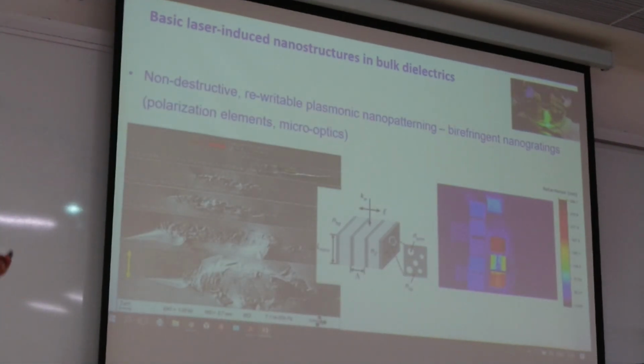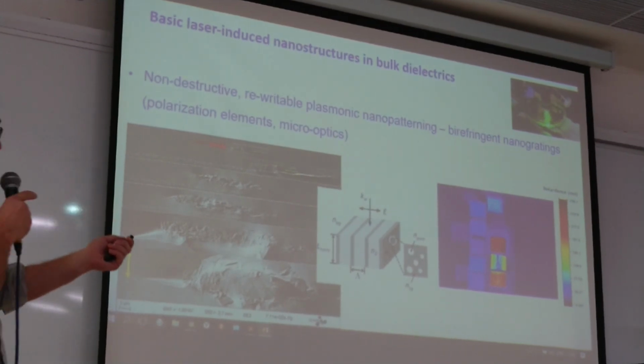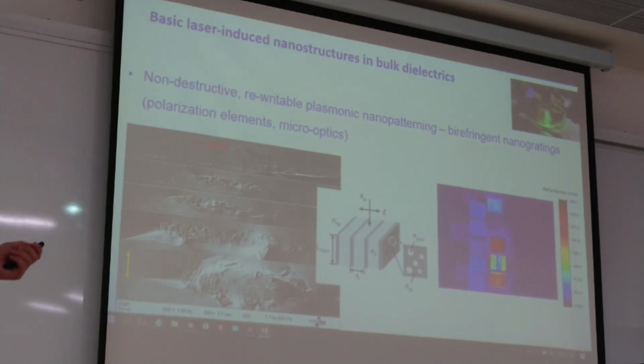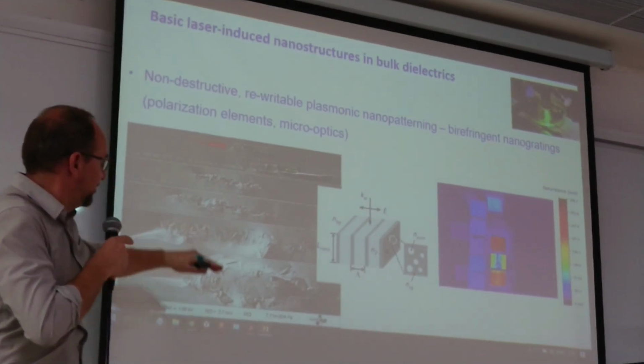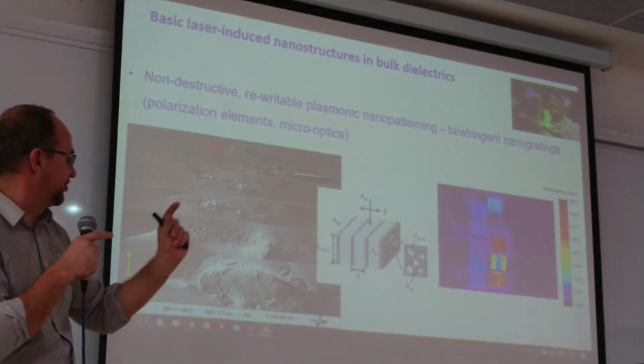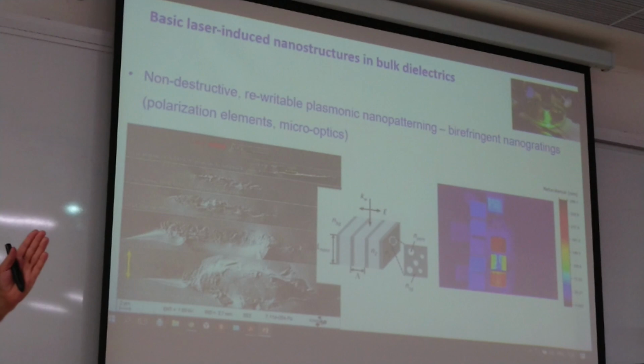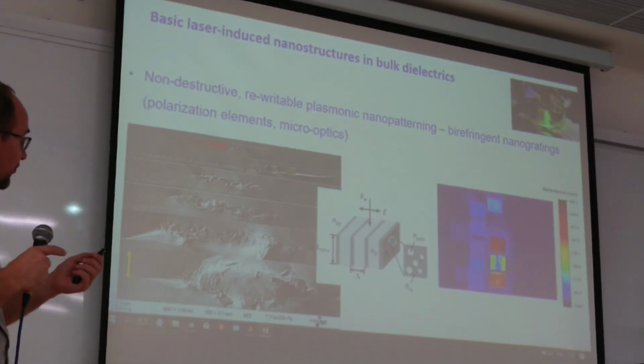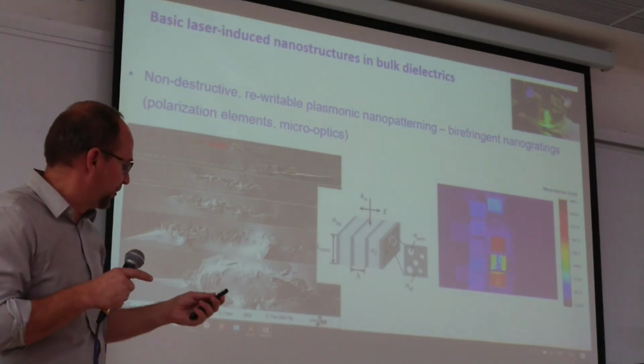Okay. And finally, people can produce, through a non-destructive plasmonic pattern, birefringent gratings inside dielectrics, and this is typically used to produce polarization elements or other micro-optics. So if the laser comes from this side, people can produce such voids or a periodic sequence of voids or even some more complicated structures depending on energy. And because of the periodic structure in this direction, this bit of material becomes birefringent, so the refractive index is changing in different directions, and for light coming through these regions, people can see a phase shift.